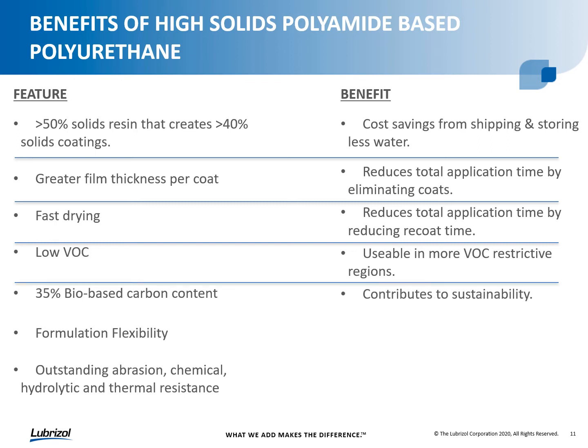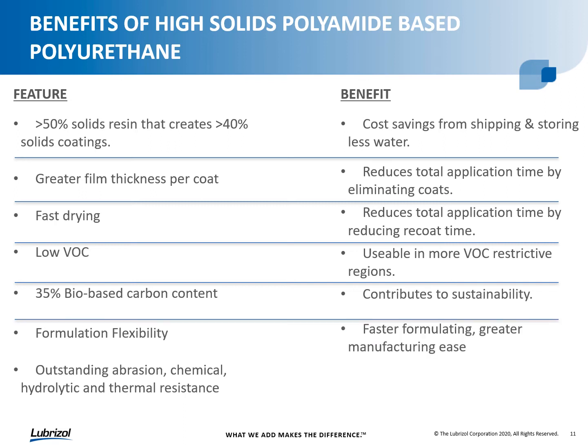We found that this product has a 35% bio-based carbon content, so we had it analyzed by an independent third-party testing laboratory, and of the carbon content in the resin, 35% of that was derived from bio-based sources or carbon that was less than 14 years old, so contributing to sustainability.